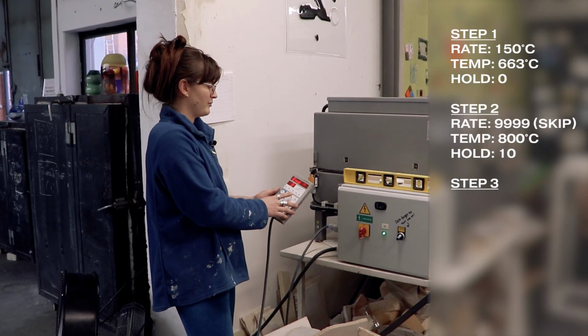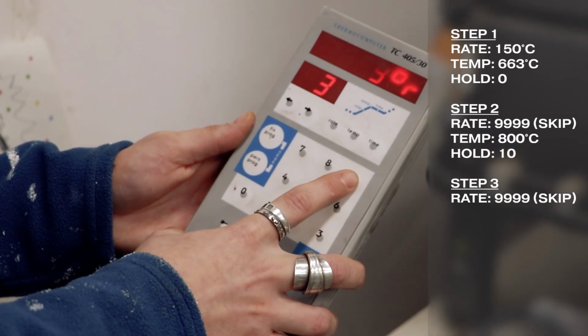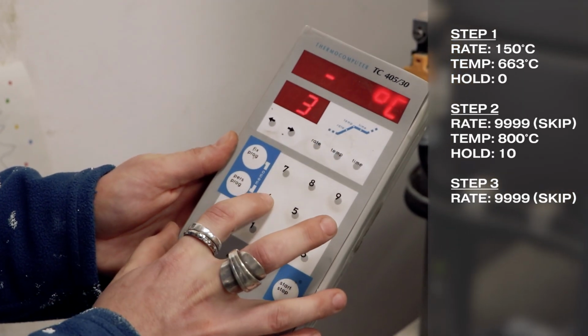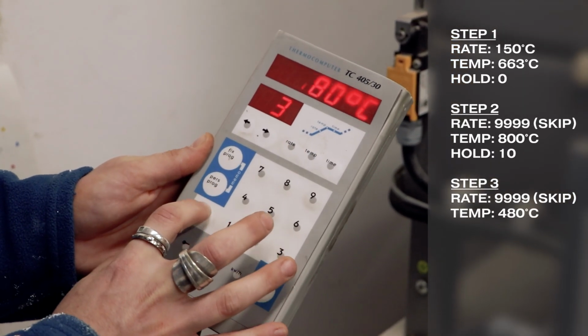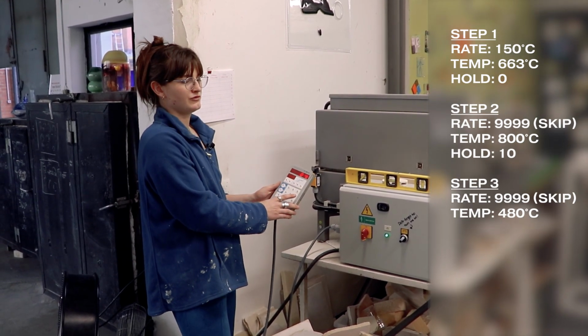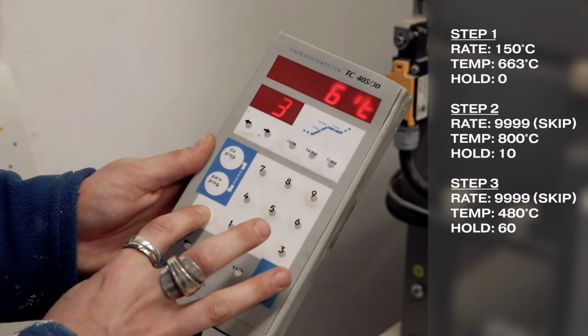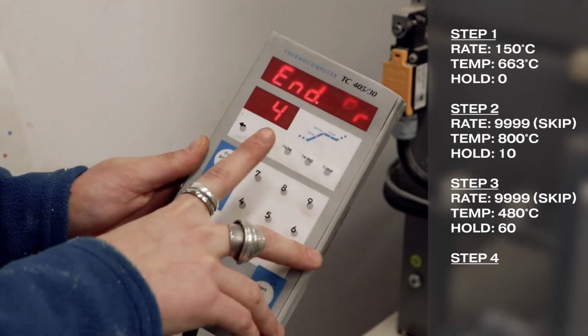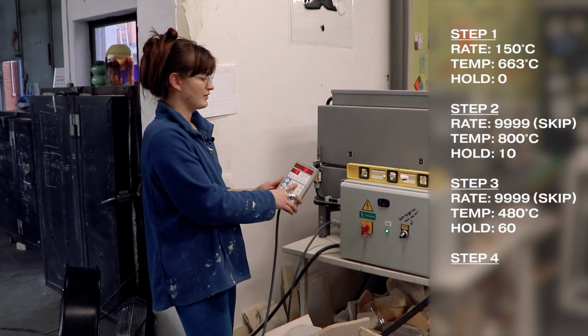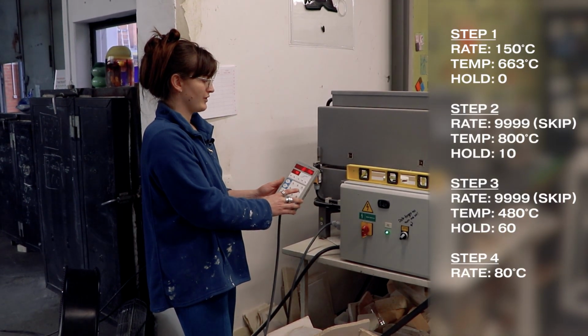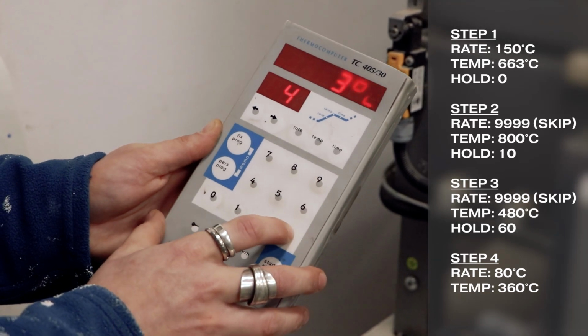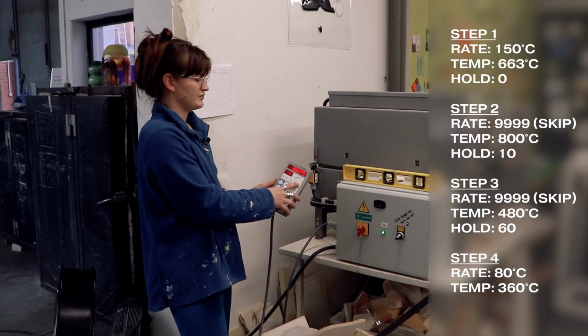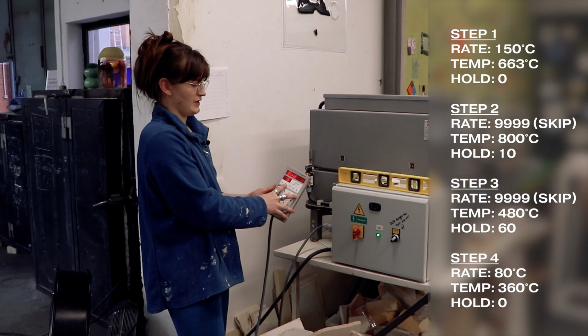Then the third step, I also wanted to go as fast as possible to temperature of 480. And here I wanted to hold for 1 hour. So I would put 60 minutes. And then the last step, I wanted to go 80 degrees per hour until it reaches 360 and no time. And then that's the end.